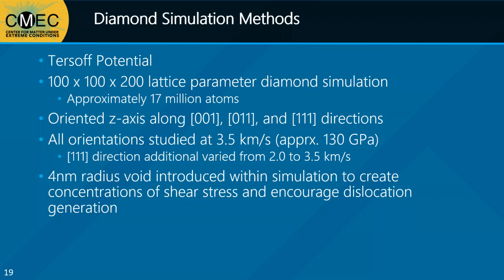This better captures the evolution of the shear components due to the wider range. This time our sample was oriented in 3 different directions along each of the 001, 011, and 111 directions to test the anisotropy of diamond under shock. Each orientation was subjected to a 3.5 kilometer per second piston velocity, which reaches around 130 gigapascal pressure for diamond. The 111 direction was additionally simulated at varying piston velocities from 2 to 3.5 kilometers per second.